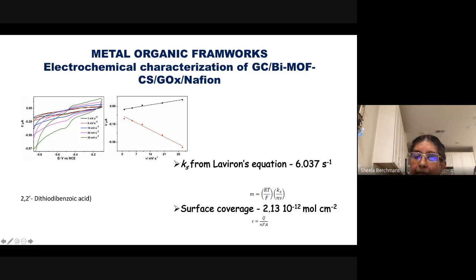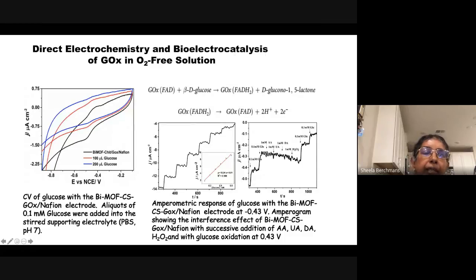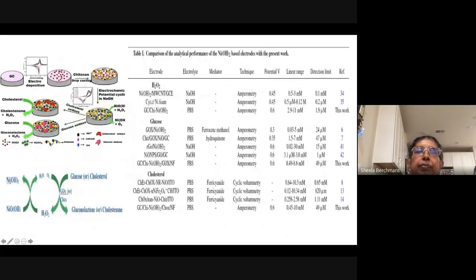The electrochemical signature of the FAD molecule is seen in the cyclic voltammogram. The surface coverage of the enzyme molecule is found to be of the order of 10 power minus 12 mole per centimeter square. And you can see how the glucose oxidation takes place in the oxygen-free solution. So in the oxygen-free solution, glucose can be oxidized. That shows the glucose oxidase enzyme is electrically wired. Oxidation occurs only through the enzyme, and no other mediator comes into play here. So we were able to demonstrate direct electrochemistry using the metal organic framework compound.